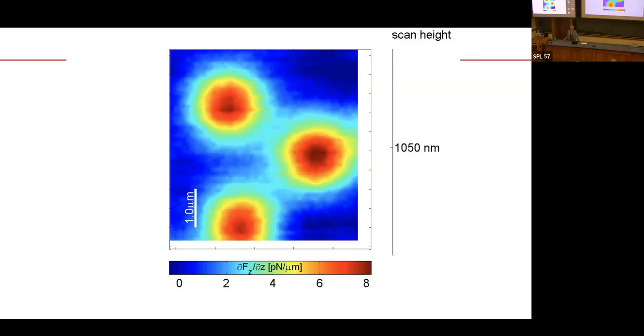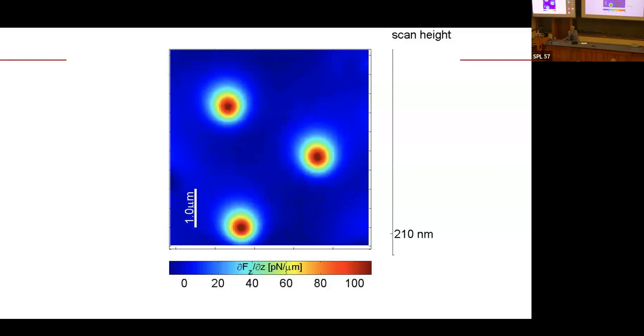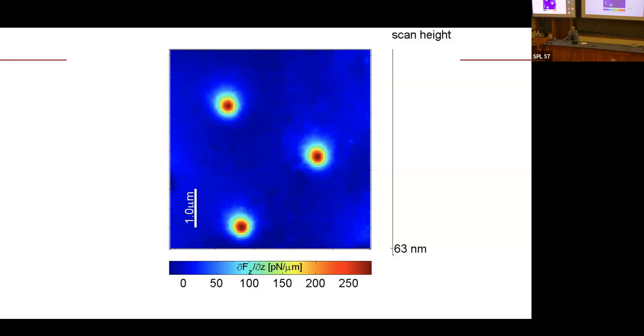But again, unlike with a tornado or a hurricane, as you come in closer and closer to the surface, the magnetic fields get more and more concentrated until finally you reach the point where you start to see your image influenced also by other forces and topographical signals associated with the surface. You have to get very, very close to the surface with a scanning probe in order to detect these individual vortices, and also to quantify both the amount of magnetic flux that they carry and what their spatial extent is.